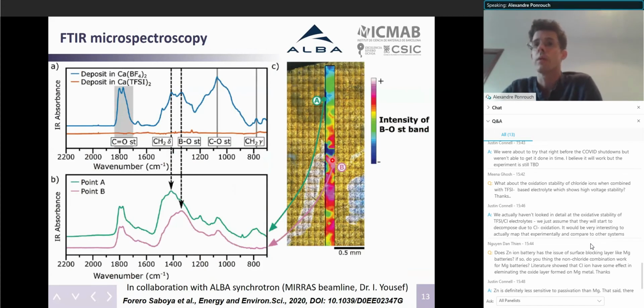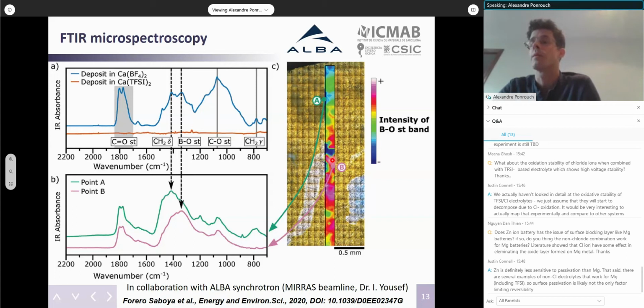Before I move to the electrolyte part, I would also like to highlight one point that we already assessed as significant for improvement of our system: the homogeneity of these passivation layers. Here you can see infrared microspectroscopy of our passivation layer that was performed at Alba Synchrotron, giving us an infrared spectra that is mostly related to the borate stretching bond.